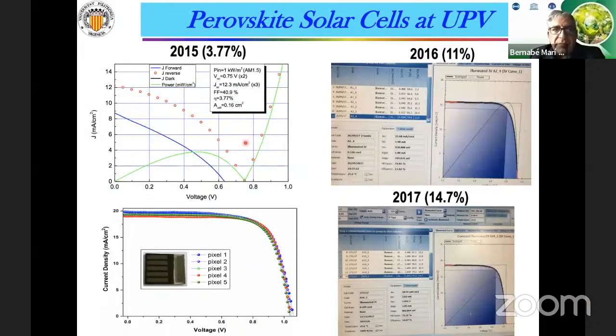Well, in our lab, this is the evolution of solar cells prepared in the Universidad Politécnica de Valencia. In 2015, our first solar cell delivered a performance of 3.77%. The next year, 2016, 11%, and in 2017, we reached nearly 15%. This is the aspect of our devices, and this slide shows the IV curve for different pixels, and the experimental and the theoretical curve of that.